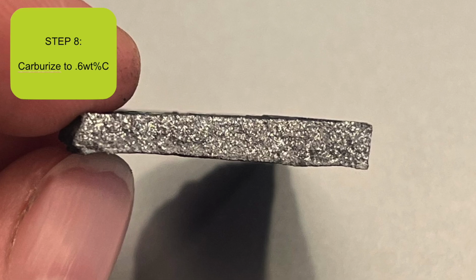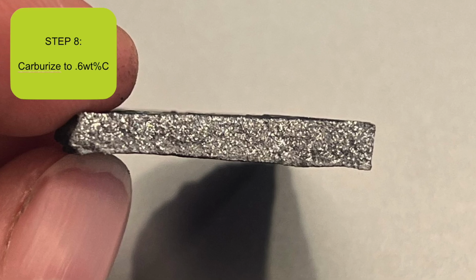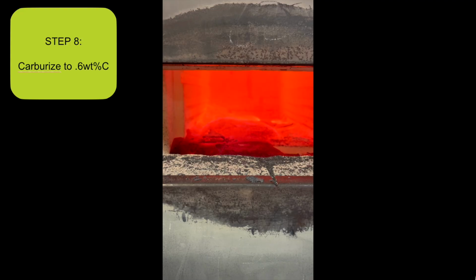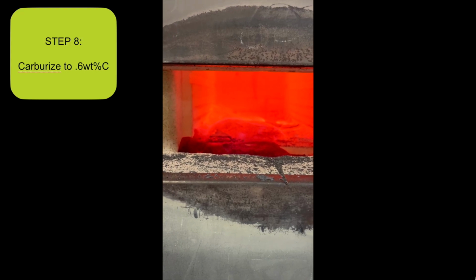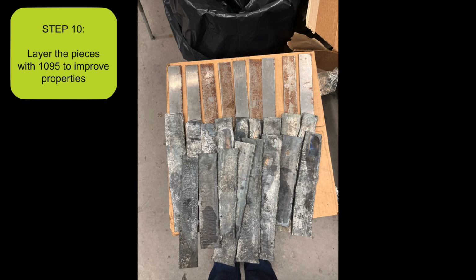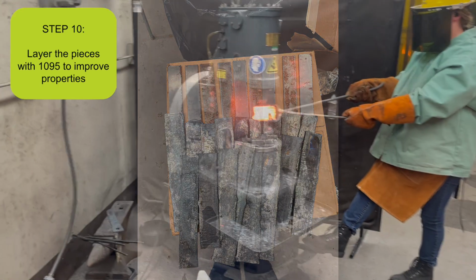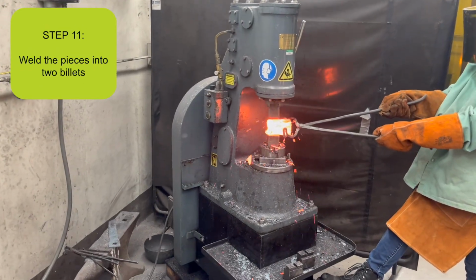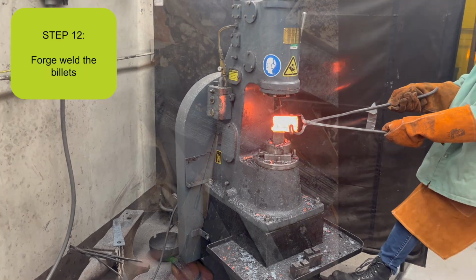We ended up using our last resort, 1000 degrees Celsius for 100 hours, and ended up at 0.53% carbon, less than our 0.6% minimum. Because of this, we elected to add layers of 1095 to improve the hardenability and structural integrity of the final blade.